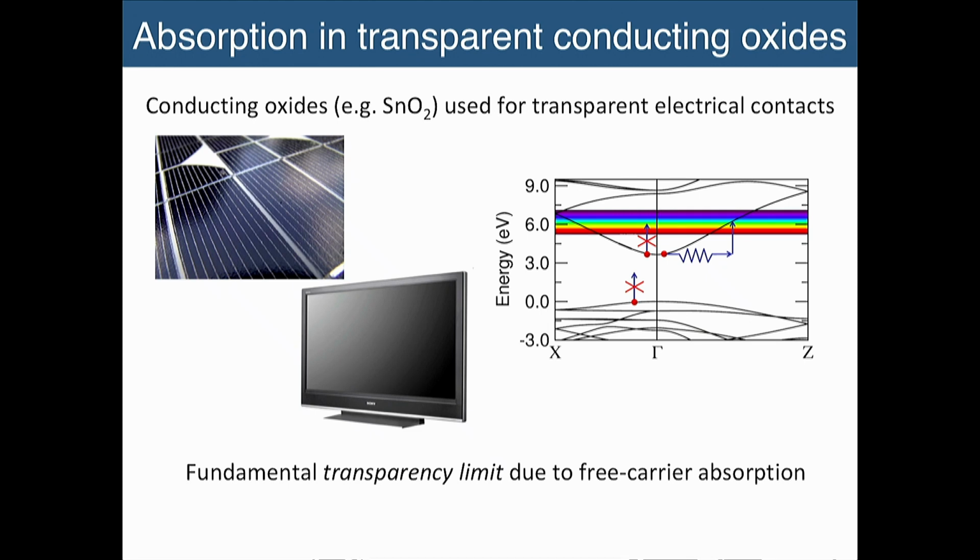It's because it's coated by a transparent contact like indium tin oxide or tin oxide or zinc oxide. So what's special with these materials? They have wide band gaps. Their band gap is at least equal to the UV energy of 3.4 electron volts, but they're doped. They're heavily doped oxides, so free electrons in the conduction band are what give you conductivity.